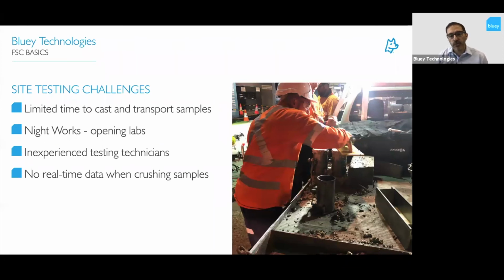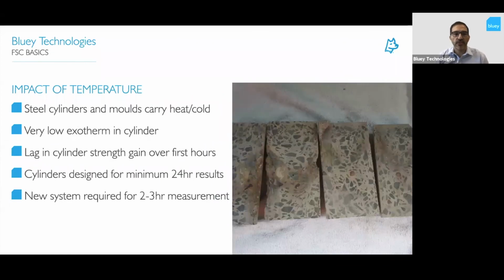It also means that you have to transport the cylinders quickly to the lab without damaging the cylinders or having an effect on them. And the chance of that cylinder being representative of what's happening in the slab is pretty limited in this type of application when you've got such fast set gain. And what we'll show tomorrow when we're talking about maturity testing is that there's a difference in what you find in cylinders compared to what you're seeing in the slab in terms of strength development. And there are ways around measuring that. So we need real-time data when crushing these samples is what it boils down to.